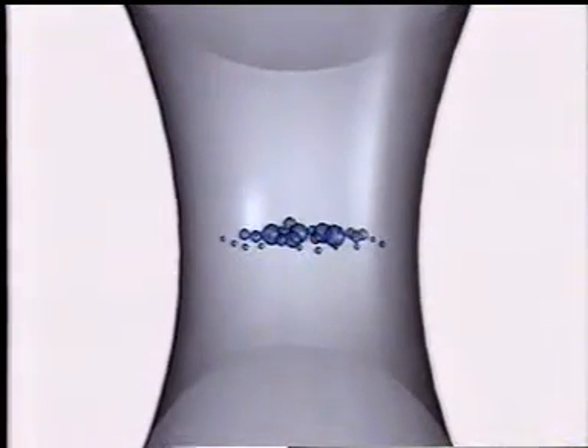The sequence of events leading to fracture in a ductile metal begins with necking down of the specimen to which a tensile force is applied. As the specimen necks down, the fracture initiates internally with the formation of microvoids in the necked region. These microvoids grow or coalesce to produce an internal crack. The final separation of the cross-section occurs by shear rupture. The fracture has a characteristic cup and cone appearance after the necking down, and the final rupture produces a shear lip, which forms the wall of the cup.